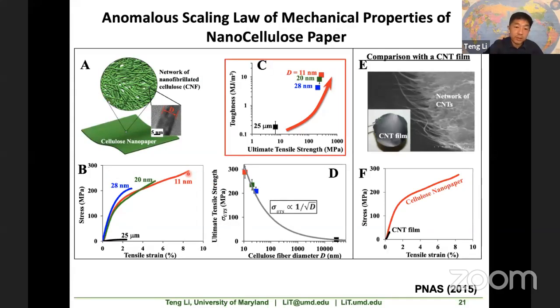Now, if you integrate the area below the curve, that is the work of fracture. And if you plot the tensile strength and the work of fracture here, this will be the typical paper you have, with thick fiber. And these three data points are the nanopaper made of much finer cellulose nanofibers. You clearly see this increasing trend. So by decreasing the building block size, you increase the strength and the toughness simultaneously.